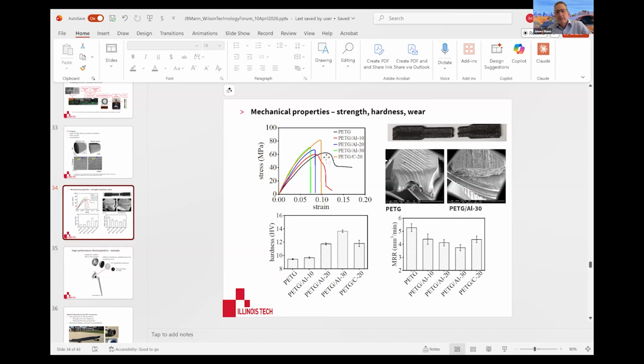There are obviously compared to the carbon fiber. So I'll point out to you the orange line is the carbon fiber, which any of us in composites, we would always obviously expect carbon fiber to outperform structurally. But the one thing I wanted to point out is that the 30% by weight aluminum metal fiber actually has a very comparable, in fact, a little bit higher modulus, which is relevant from a design perspective, because we design for systems to operate in the range of elastic compliance.